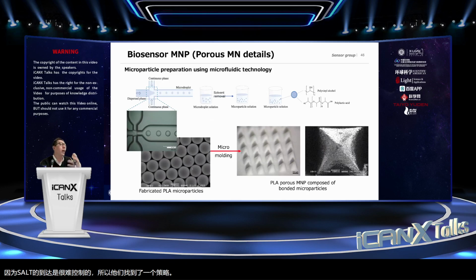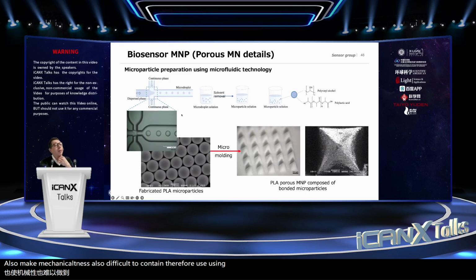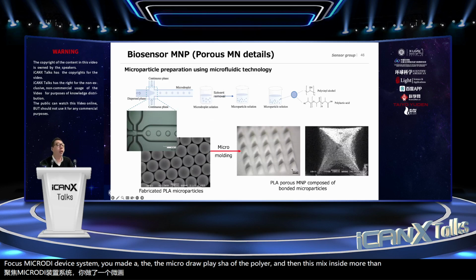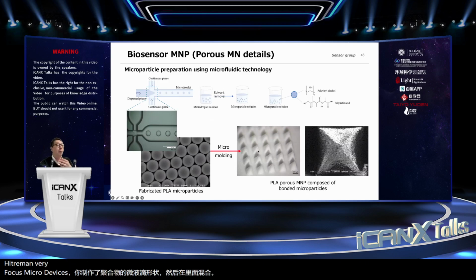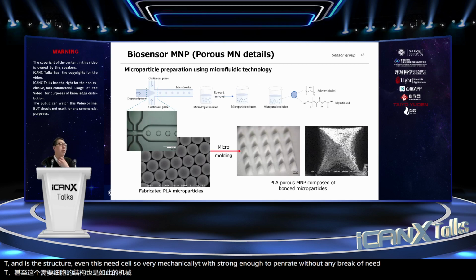Also, mechanical stiffness is difficult to maintain. Therefore, we are using, for example, fluid-focusing microfluidic devices. You make micro droplets of the polymer, mix them inside the mold, and apply some heat treatment. Very easily, you can get good control over the porosity and this interconnected structure. Even the needle itself is very mechanically stiff, strong enough to penetrate without any breakage of the needle, right?